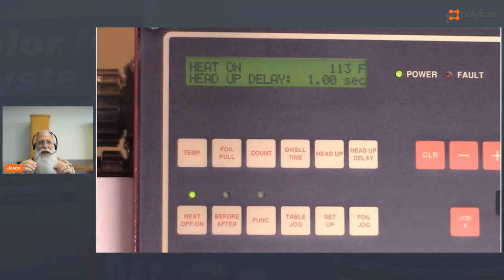The delay itself, we're looking for about a 1/4 inch gap between the label after the dwell, about a 1/4 inch gap, and then we want to pause the machine traveling any more vertically. And we want to pause it for 1 or 2 seconds. And that allows the plastic label and the skin of the plastic part to reach a solid again. We're reaching the melt temperature of these two materials, so you don't want to immediately rip the carrier film off, or sometimes you can have some sticking of that carrier. So by using a delay of a second or two, that allows everything to come back to a solid state and the carrier film to remove easily.